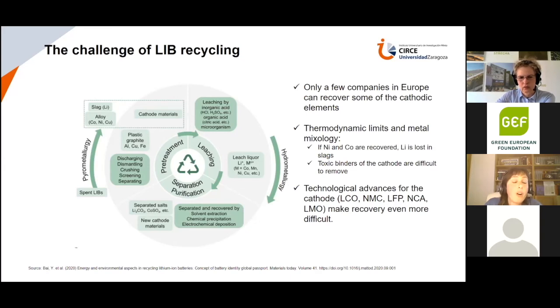First of all, there are only a few companies in Europe that can recover some and not all of the cathodic elements. We need an infrastructure to recover all such elements. Then there are thermodynamic limits and metal mixology, because as I said, if you go through the pyrometallurgical route, then you will lose all the lithium, for instance. And then you also have toxic binders in the cathode, which are difficult to remove